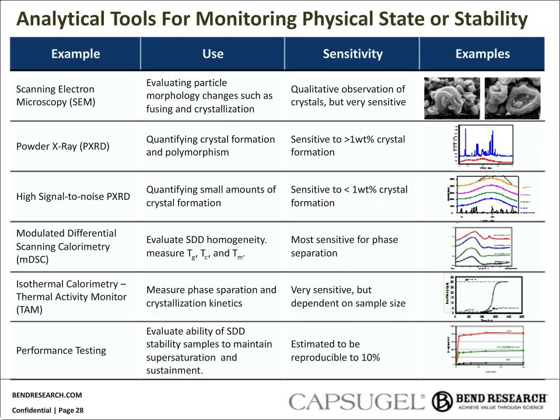So early on in the screening process, first we'll go into, here's just a general description of some of the analytical tools that we'll use for monitoring physical state or stability. Some of the examples, like scanning electron microscopy, that's a very qualitative technique, but it's probably the most sensitive technique on this list, in that typically crystals will form on the surface of SDD particles because they don't have to suffer the energy penalty of pushing a high TG polymer out of the way to grow. We also do a lot of modulated DSC, again looking for phase separation. And then, as I'll talk to later, thermal activity monitor, isothermal calorimetry.